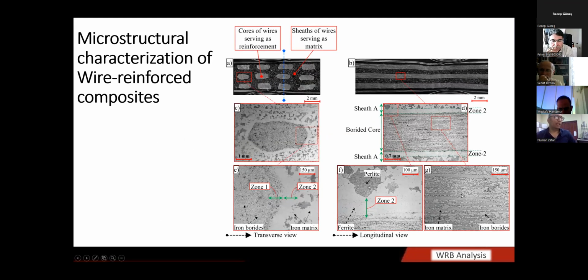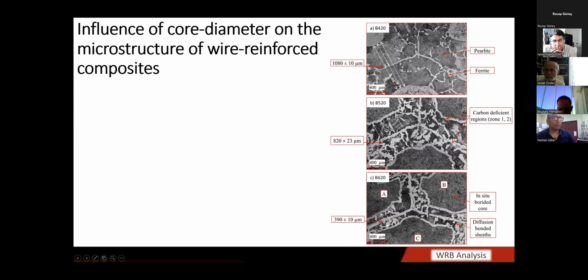First things first, try to see if the iron boride phases have formed. Okay, iron boride phases have formed. They are elongated as we had expected. Good news. The microstructure at the center of the core is different from the region at the interface with the sheath. Also, we can see the microstructure of the sheath which is in contact with the core, these white regions. We have not done anything intentionally there, but the sheath which was in contact with the core has grains, but they don't have any pearlite structure. You can see it in all wires.